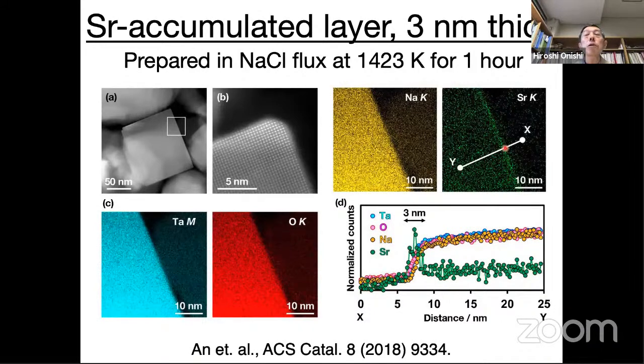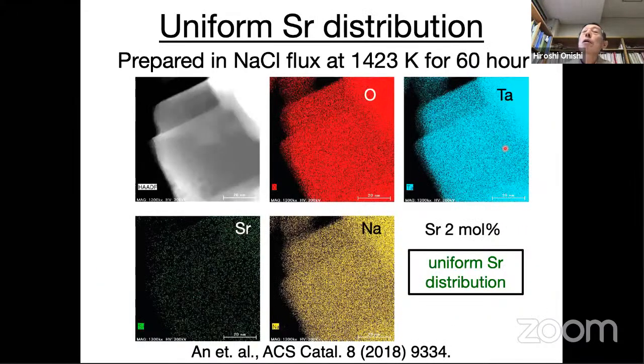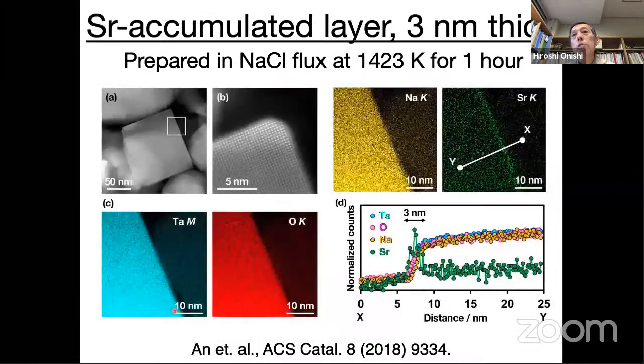This was observed in the 1 hour heated sample, and we compared it with the 60-hour heated photocatalyst, and we found no strontium enrichment. Strontium was uniform everywhere. So now these TEM microscope results showed us that strontium enrichment at the surface was the key to increase the number of excited electrons.